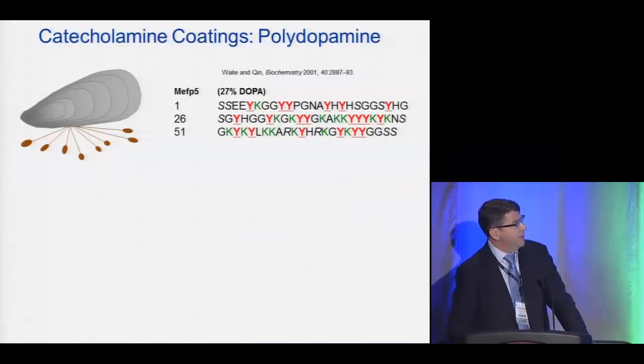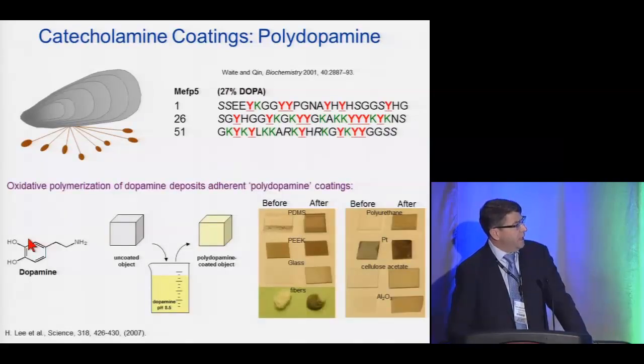So one of these I will mention, which is inspired by one of the muscle adhesive proteins, MEFP5, which has the highest DOPA content, but also has the highest lysine content. So you can think of this as a polycatecholamine polymer. And so we developed a surface modification strategy that derives from a small molecule. You can think of this dopamine molecule, which has the amine derived from the lysine, the catechol from the DOPA, as a monomer. And it's a very simple surface modification strategy.